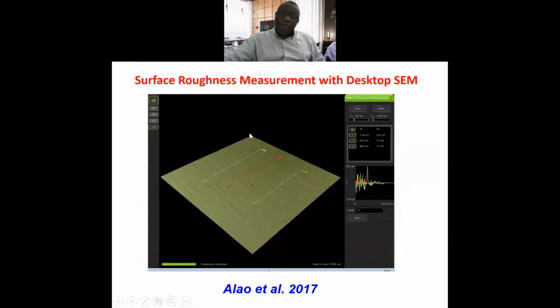You can see this is the machined surface. The surfaces were measured across, perpendicular to the machined surface. You can see the machined surface, and this is the profile of the measurements. So three places were taken, and the average surface roughness and the maximum surface roughness were carried out. XRD results show that lithium metasilicate is the main crystal for the first material. When this one is polished and sintered, the sintering process has converted the lithium metasilicate crystals to lithium disilicate crystals. Also, for sintering and glazing it is still lithium disilicate crystals.